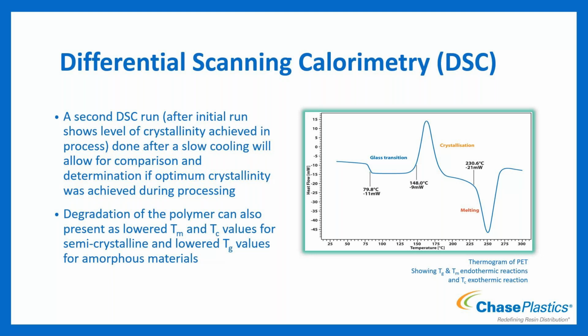And then, a lot of different materials have different graphs, but overall you'll see an initial dip, which is going to be your glass transition. This particular graph is for PET, so it is a crystalline polymer. You can see it has a crystallization peak. So you have your initial dip for glass transition of this one. Then you have an exothermic reaction, which is your TC here. And then again, the melting one, which is going to be your endothermic.